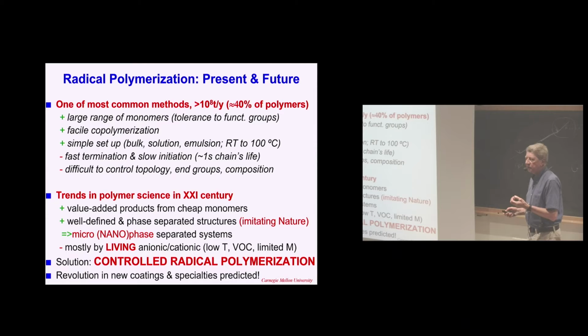However, the problem is that formally radical polymerization should not occur at all, because every encounter between two radicals is termination. And this encounter happens with diffusion-controlled rates. So as quickly as two molecules can diffuse, they instantaneously terminate. So in order to suppress termination, one needs to keep radical concentration very low, parts per million or parts per billion under some conditions. So how to do it? How to work with such a low concentration?